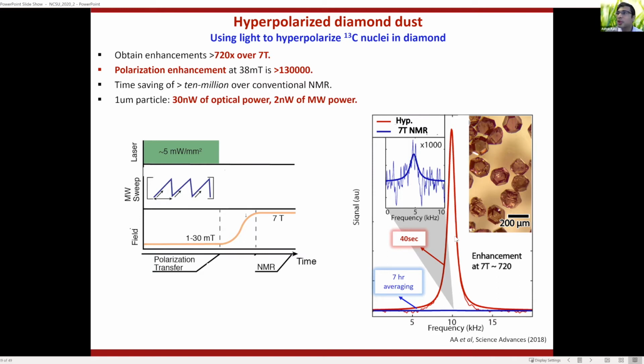And you can show this polarization in many ways. You can say how much it's polarized over a particular field, it's pretty large, or the effective time savings and so forth. But overall, this should not come as a surprise, because the NV centers are very highly polarized, and what you're trying to do is transfer the spin order in the NV centers to the nuclear spins. The bigger surprise is that the NV centers in this random collection of particles are polarized randomly, and yet all the carbons are polarized in the same direction. I think that's the big surprise, and I'll show you why that works.